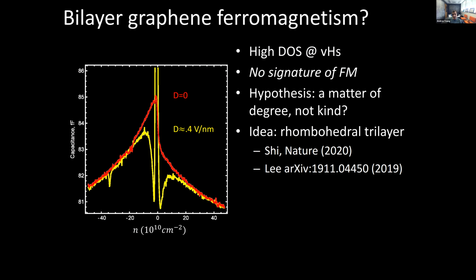But the hypothesis that this talk starts from is that actually this is a matter of degree and not of kind. In other words, for whatever reason, the density of states in bilayer graphene is simply not quite big enough for anything interesting to happen. The Stoner criterion is a relatively sharp boundary where you get a first order phase transition to a magnet, and Tc in a superconductor is exponentially sensitive to the electron phonon coupling and therefore the density of states. So it's certainly possible that all of that physics does indeed manifest in these types of systems, but doesn't manifest in this particular system. And in fact, this seems to have been borne out already before we started this work